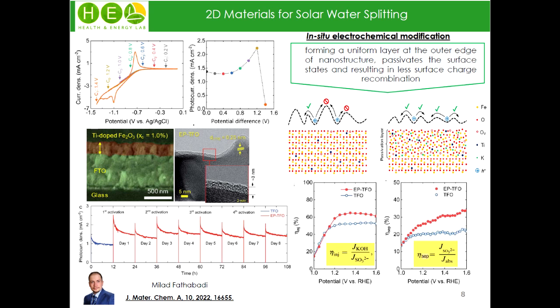Sometimes it's a preferred morphology, usually formed in the hydrothermal process, if we don't use any additive or surfactant in the system—to avoid residue on the final photoanode, mainly it's the preferred structure. If you follow, for example, the works by Sivula and Gratzel in EPFL, they also developed hematite for tandem cells, in this format. Correct.